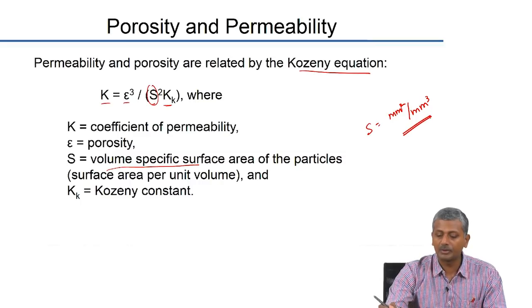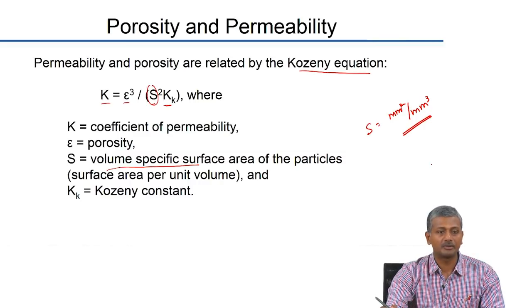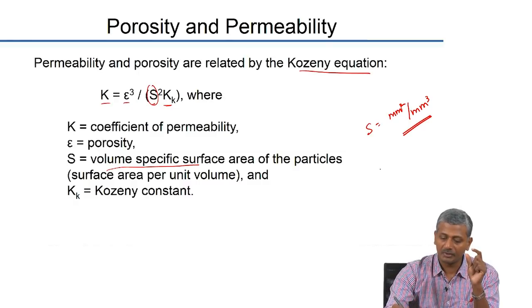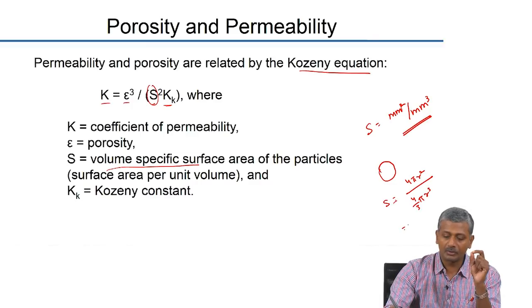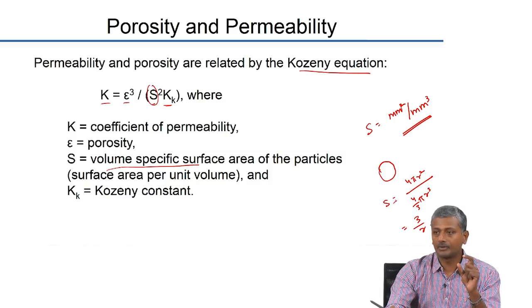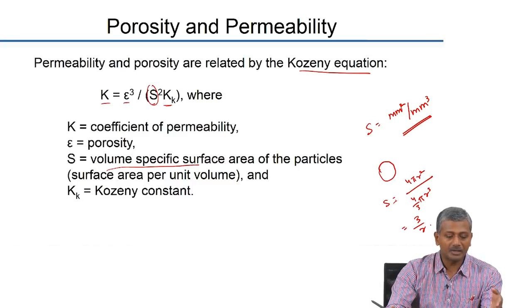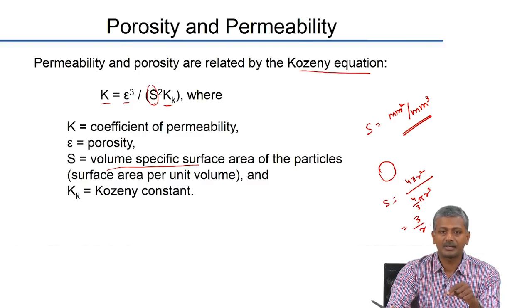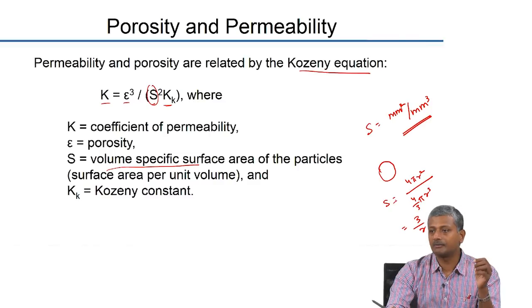the units of surface area per unit volume will be square millimeter per cubic millimeter. So if we take a sphere, for example, for a sphere, what is this S equal to, what is the surface area of a sphere? 4 pi r square. Volume is 4 by 3 pi r cubed. So that is equal to 3 by r. Surface area per unit volume for a sphere is 3 by r. Okay. So like this you can work out the surface area for different geometries. Okay. So here again, surface area of the particles we are considering, the particles that are making up the solid phase around the porosity, okay, because that is going to now define the kind of interconnectivity between the pores.